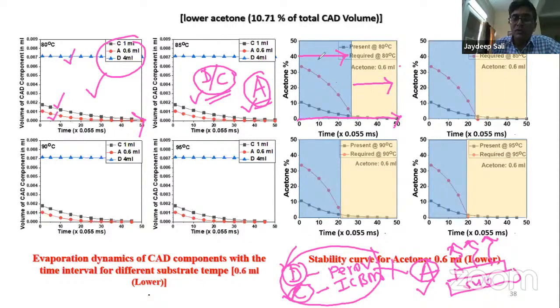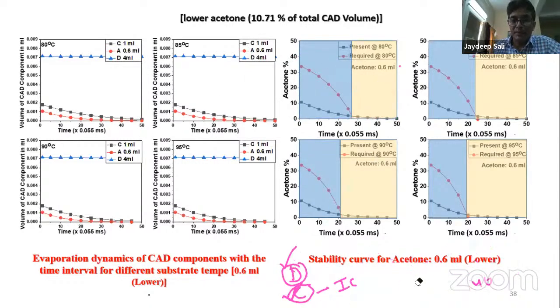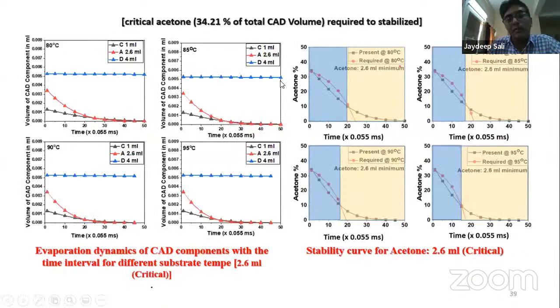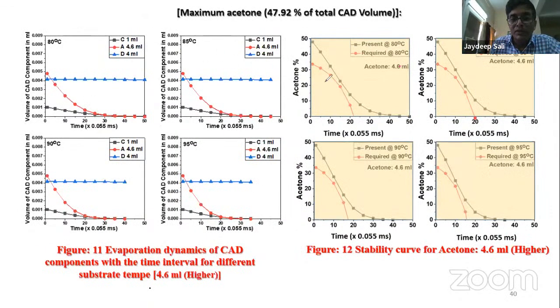Of course, this time period is a function of how much acetone is added initially for the microemulsion formation. If we increase the proportion of acetone in the microemulsion formation, this time period will decrease. In the next slide, I will show you. If we increase the acetone proportion initially, then the stable time has increased, you can see. Now, if we still increase the acetone proportion in the microemulsion initially, then you can see in this diagram that the emulsion is stable right from the beginning of the solidification up to the complete solidification.